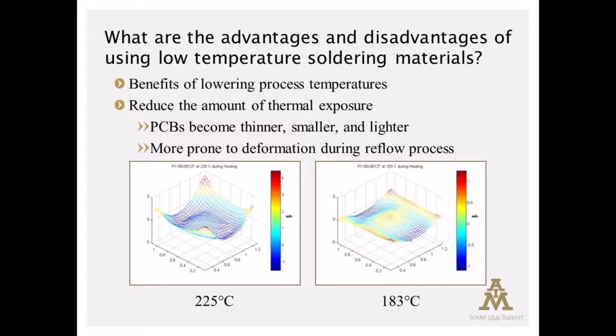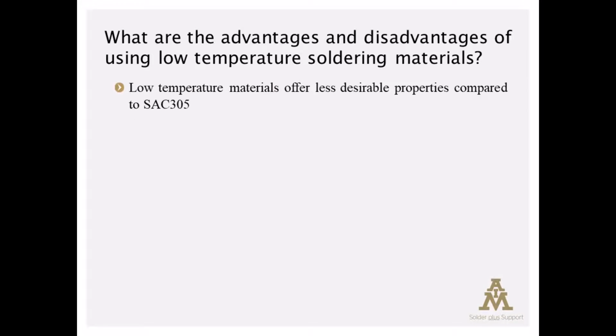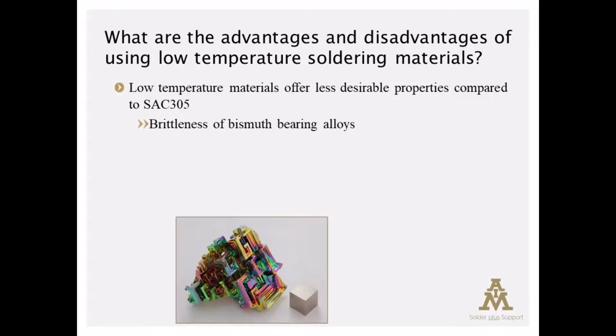Now, these materials have other properties that are somewhat less desirable than the SAC 305 that's currently in use. And those have to be taken into consideration when determining if a low temperature process is appropriate for the product. The most concerning of the low temperature alloy properties is the brittleness that's imparted when bismuth is part of the alloy system. And bismuth is used in all of these low temperature materials to some degree. So it's a tin bismuth plus system, and those systems are very brittle as a result of the bismuth content.